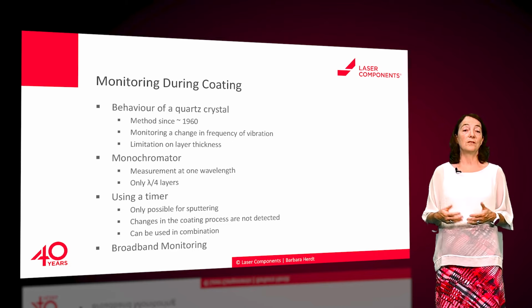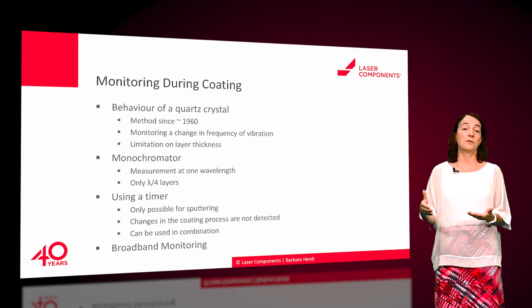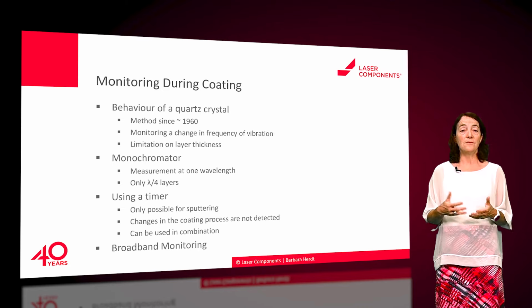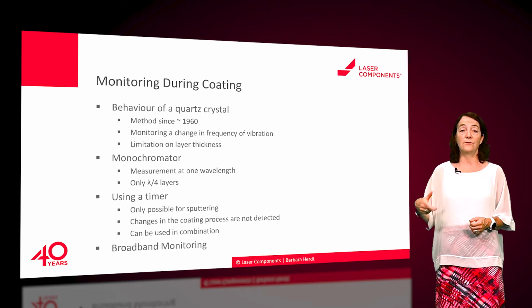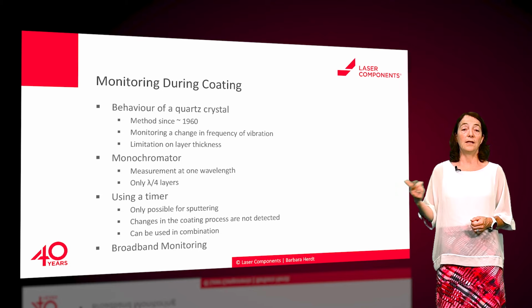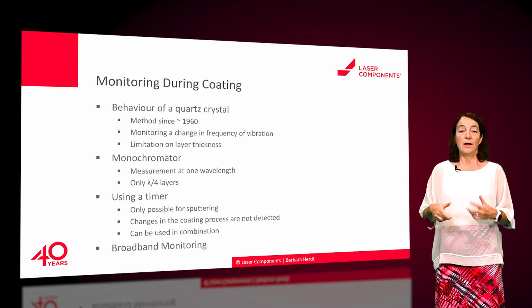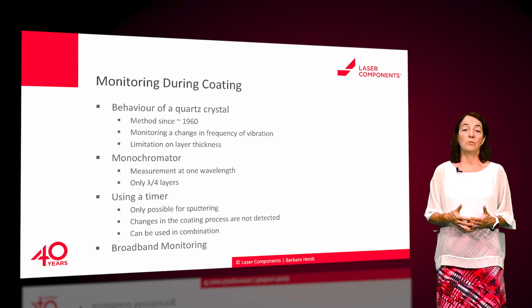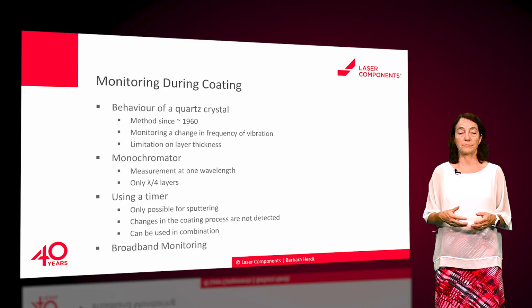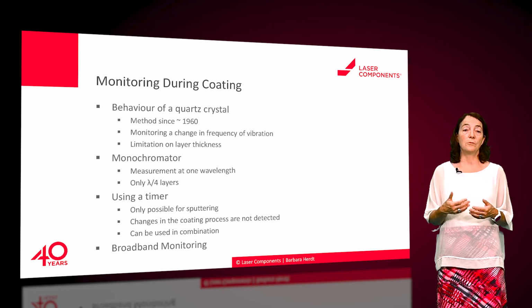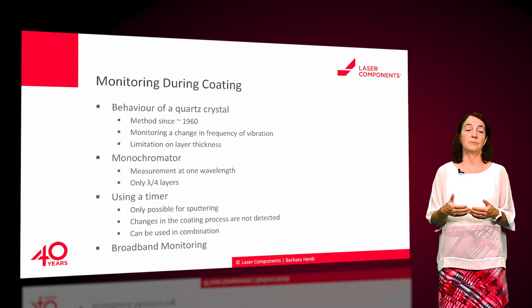But this is only possible for sputtering technologies, as this has a constant sputtering rate. If there is any failure during the coating process, this will not be detected until after the coating is completed, at the outgoing spectral measurement on the witness sample. However, this is a good method to be used in combination with other methods. The trend, however, is now to work with a broadband monitoring system to control the spectral behavior.